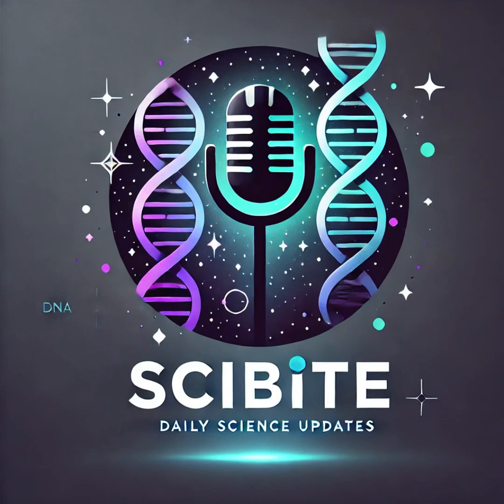Okay, this is where it gets really cool. And it's the core finding in the research. It's not just about the Ba8Ni6Ge40 material as it starts. It's about what happens to it when it's actually doing the job. What do you mean what happens to it? It transforms. Like fundamentally changes its structure during electrolysis. They used some pretty advanced techniques, X-ray absorption spectroscopy while it was running. In situ, yeah. Watching it live. Exactly. In situ XAS plus electron microscopy afterwards. And they saw that when you put these particles in the alkaline electrolyte and apply the voltage, the germanium and the barium atoms, remember, they make up the cage walls and the trapped atoms inside.